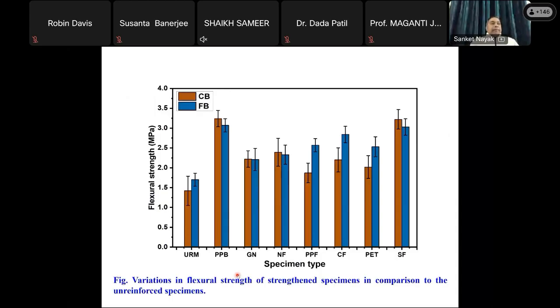Now these are the variations in the flexural strength of the strengthened specimens in comparison to the unreinforced specimen. This one is the clay brick and this one is the fly ash brick, and this is for the unreinforced one. Here you can see the PP band outperformed all the strengthening techniques, whereas the steel fiber outperformed all the other internal techniques. But the other fibers, that is PET fiber, coir fiber, and nylon fiber, have also performed very well.